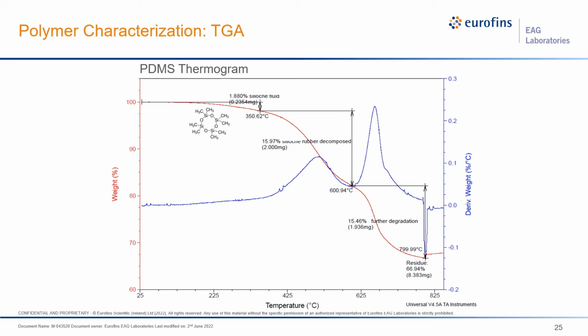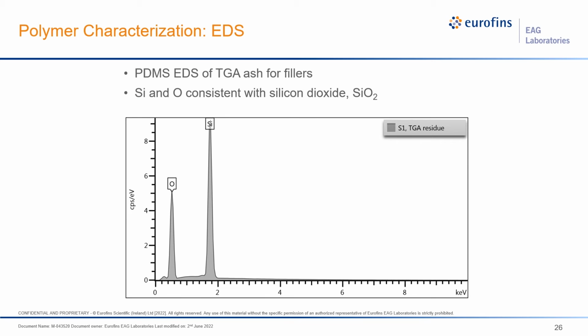At this point, we can usually conclude that this is going to be some sort of an inorganic material, as most organic compounds decompose well before 800 degrees. So we suspect that this is some sort of filler in this polymer, but what is it? For this, we'll again introduce another technique known as EDS, or energy dispersive X-ray spectroscopy. This is a technique that allows us to detect what the elemental composition of the sample is. And just as we suspected, we aren't seeing any carbon in this residue. All the material that we're seeing is silicon and oxygen.